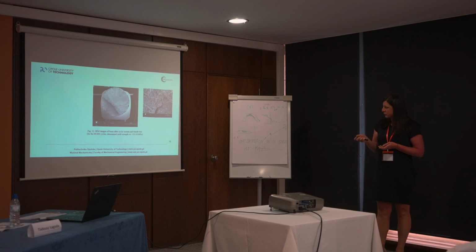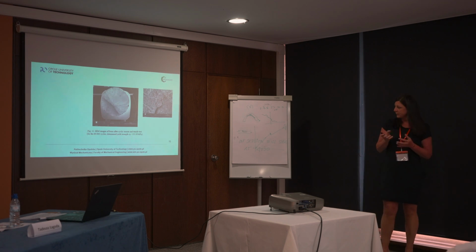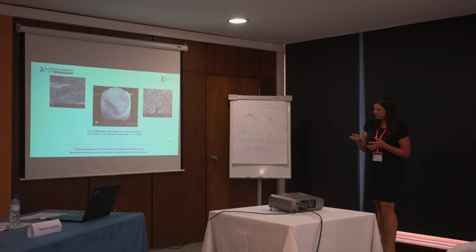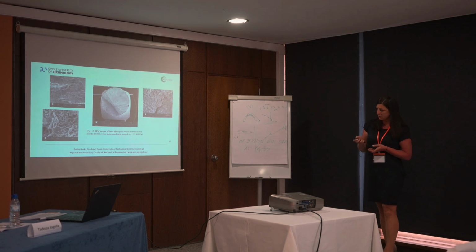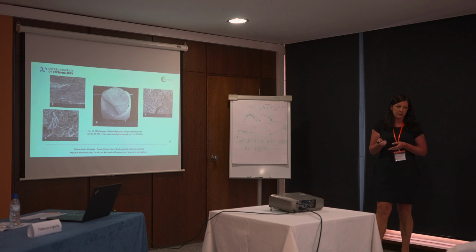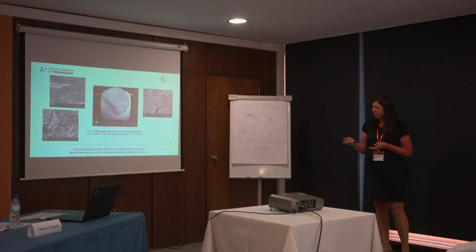The fatigue initiation for brass is characterized by a rough surface and an irregular fault propagating in a random direction. This picture shows the fatigue zone fillet with micro areas of strain with different orientation, and the next picture, taken at a magnification of more than 12,000, shows the residual zone.